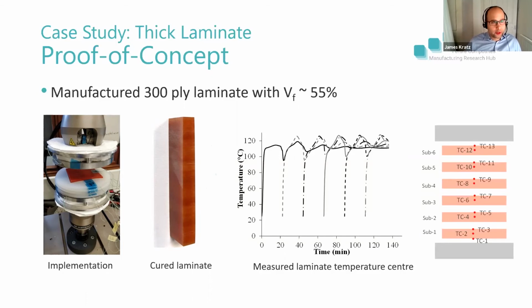And I'll remind you that this process took a little over 2 hours, but it was still a good 30 or 40 minutes faster than a conventional process. I'll just note that there was no debulking applied whatsoever in this instance. So we just laid up the laminates, chucked them into the press, squeezed it at elevated temperature, and the results that you see are the results that we obtained.